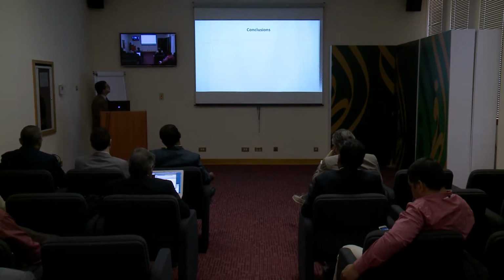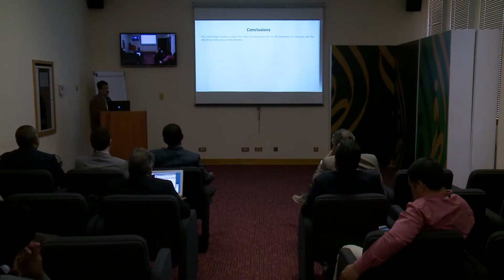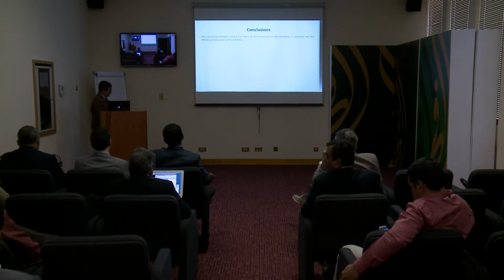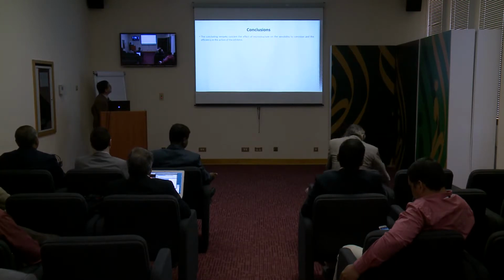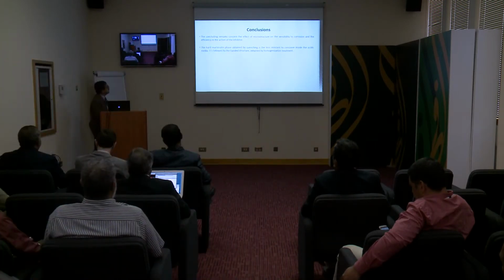So, in conclusion, the main remarks concern the effect of the microstructure on the sensibility to corrosion and on the efficiency of the action of inhibitor. The hard martensite, which is obtained by rapid cooling, is much harder and is less resistant to corrosion inside the acidic media. It's followed by the banded structure obtained by the homogenizing treatment.